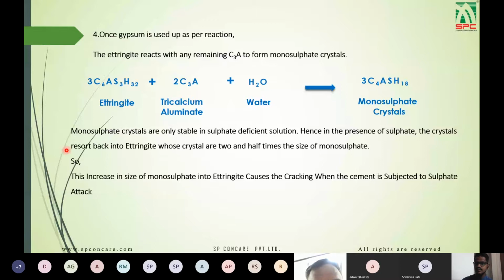So what happens if the concrete is subjected to sulfate attack? These monosulfate crystals again revert back into ettringite, which is 2.5 times the size of monosulfate. This increase in size of the monosulfate into ettringite causes cracking when the cement is subjected to sulfate attack.